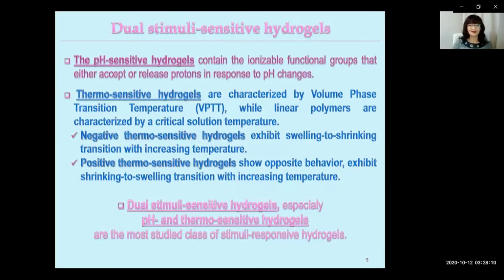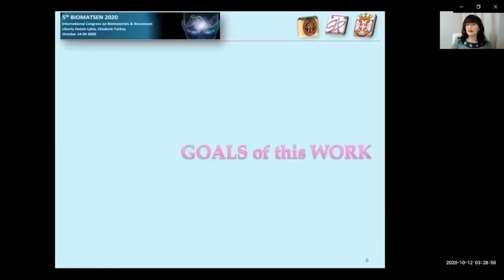Thermosensitive hydrogels are characterized by volume phase transition temperature, while linear polymers are characterized by a critical solution temperature. Negative thermosensitive hydrogels exhibit swelling to shrinking transition with increasing temperature. Positive thermosensitive hydrogels show opposite behavior, exhibiting shrinking to swelling transition with increasing temperature. Dual stimuli-sensitive hydrogel, especially pH and thermosensitive, are the most studied class of smart hydrogels. And what are goals of this work?